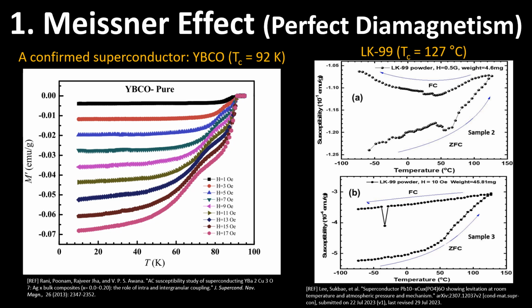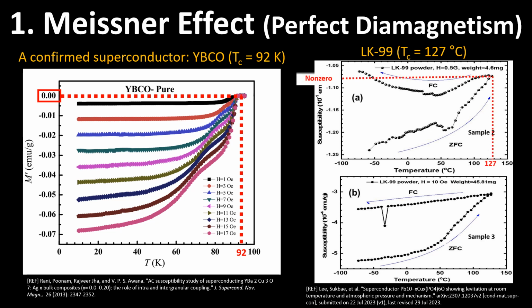The graph on the left is a magnetization measurement graph of YBCO, which is a confirmed high-temperature superconductor. The critical temperature of YBCO is about 92 Kelvin. And you can see a clear transition from zero or a slight positive to negative at the critical temperature on the left graph. In contrast, LK-99 on the right already has a negative magnetic susceptibility around the claimed critical temperature of 127 degrees Celsius in the paper and is decreasing, clearly not showing a clear transition that a superconductor should have. This is generally the characteristic of a typical diamagnetic material.